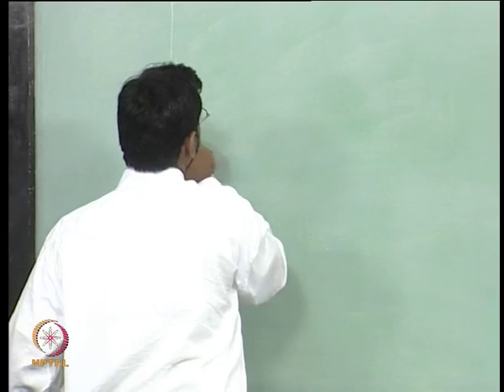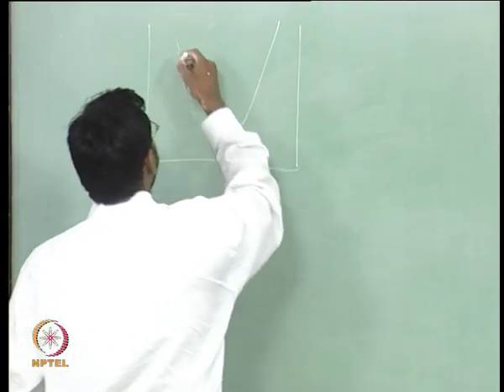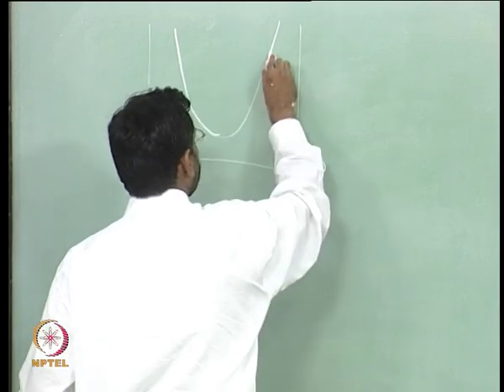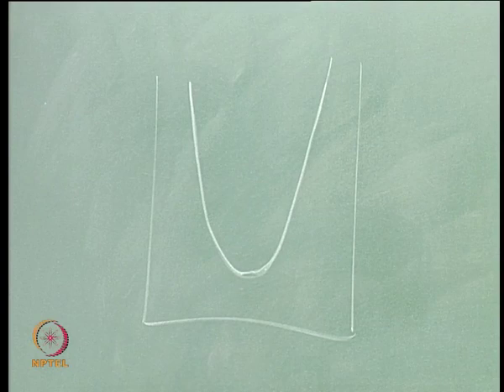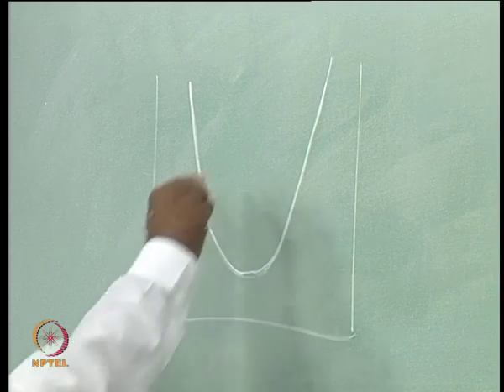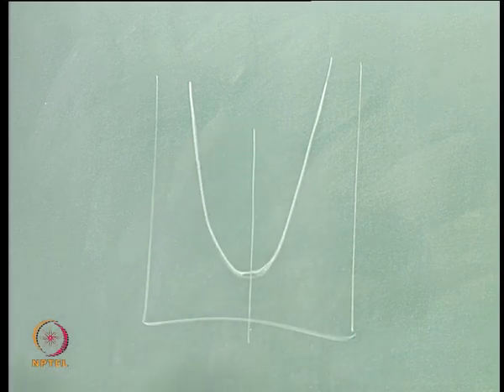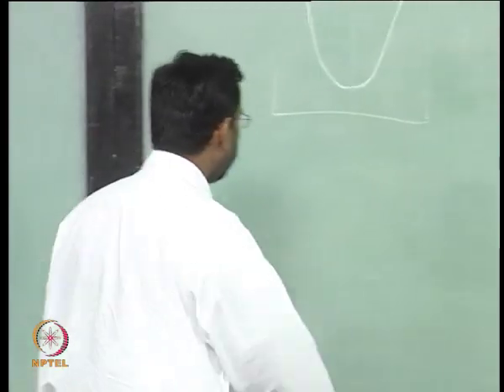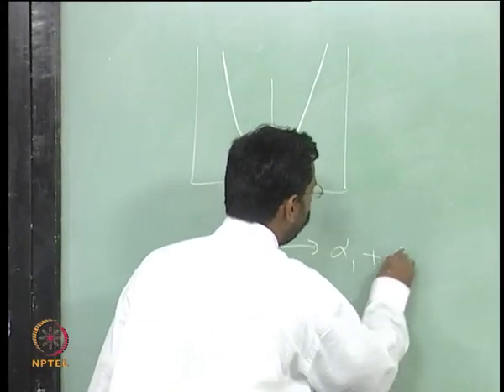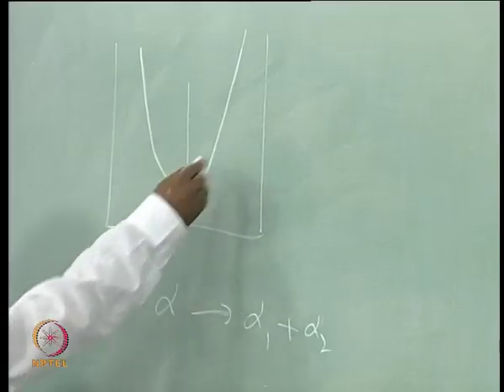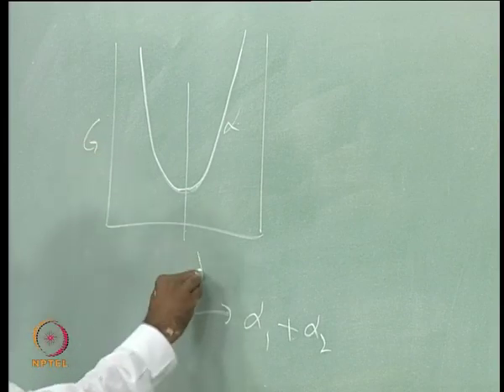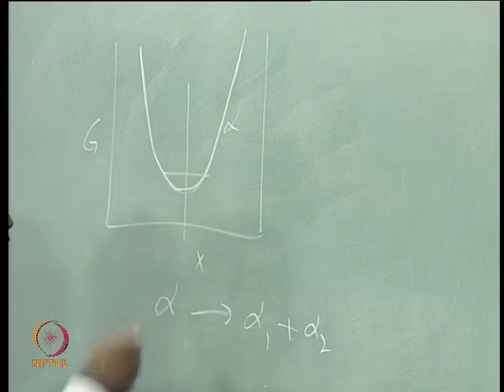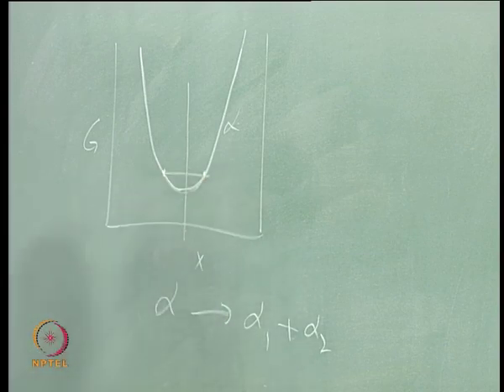Whenever a free energy curve looks like this, this phase is called a stable phase. Why? Because if I take an alloy of this composition, if this alloy wants to decompose into two different compositions of the same structure, that is what the decomposition means. That means alpha giving you alpha 1 plus alpha 2. If we call this the free energy of alpha, g versus x, if it splits into two, one with a lower composition, another with a higher composition, so that the overall composition remains the same.